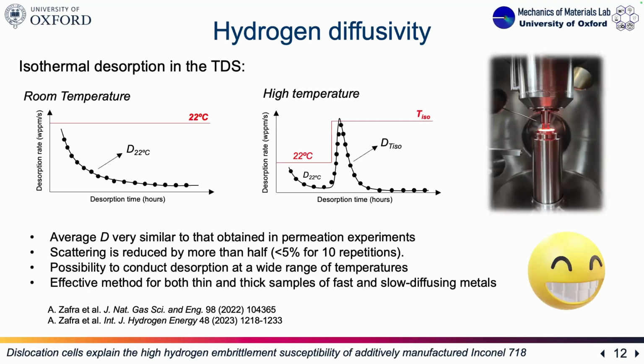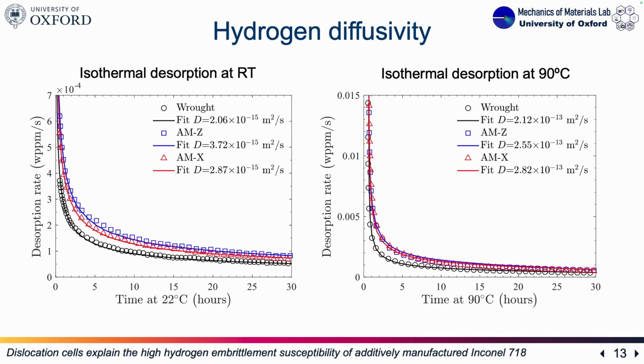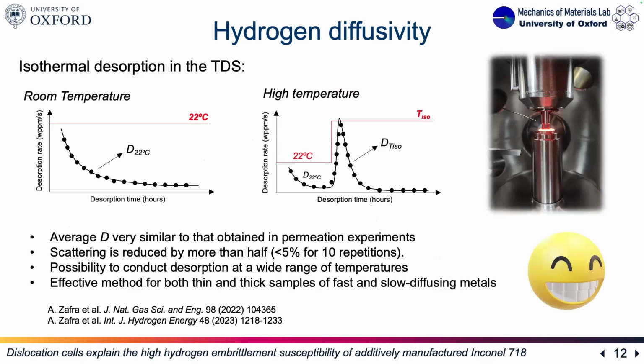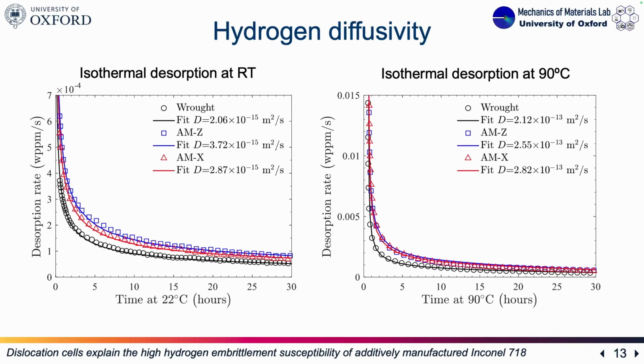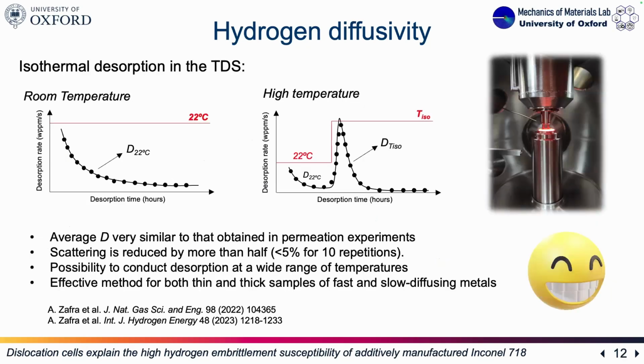Sorry, I have not said the name. It's isothermal desorption. So basically, you place the sample on the TDS, you keep it at a constant temperature, and you have a desorption profile that you can fit. We have done that at room temperature and then higher temperatures, in this case up to 400 degrees, which is really challenging when you have a permeation apparatus.